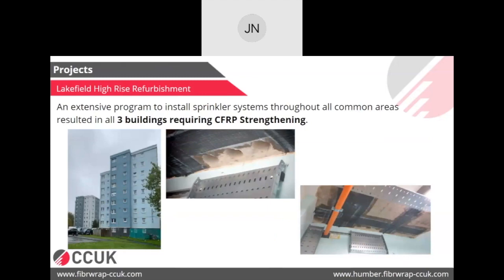So this is from a tower block, a council tower block from Wolverhampton Council. As we all know, after the unfortunate tragedy of the Grenfell Tower, it is a requirement now for all the councils to try and put a sprinkler main in all the tower blocks and change the facade as well. So to put this sprinkler main, they need to core through existing RC slabs, and we all know that these tower blocks are occupied, so you cannot go with the trimmer steel option there and do these kinds of service penetrations. So FRP is the best and easy option there to strengthen these slabs for the loss of rebar or the additional moments generated in the surrounding area, and that was done there.